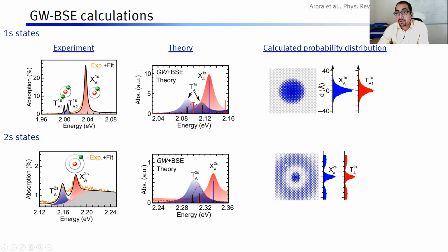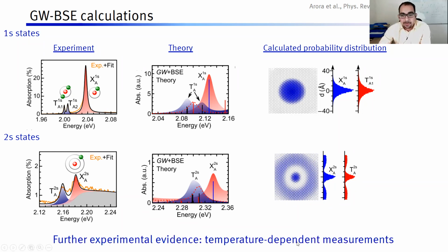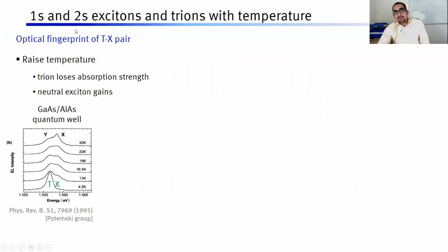However, we need more experimental evidence, because just looking at a peak in any experiment does not mean anything. We have to do more. So for that, we go to a well-known thing, which we found in literature. In 1995, it was established that if you have a trion-exciton connected pair, and if you raise temperature, then the trion starts to lose its strength, whereas exciton starts to gain for some reason, which I will explain. So essentially, for a connected pair, with raising temperature, exciton should gain strength, whereas the trion should go down in strength. Why does this happen?